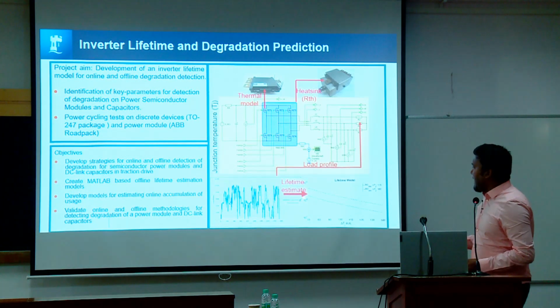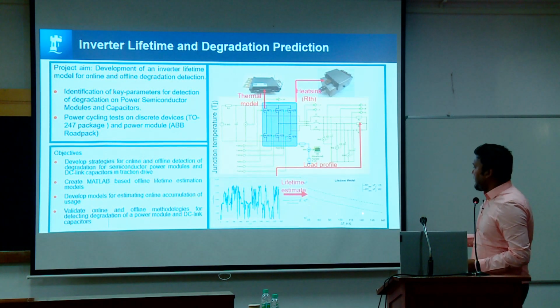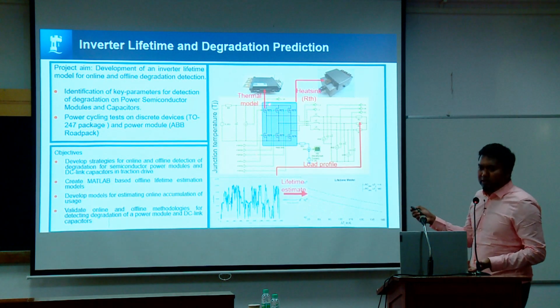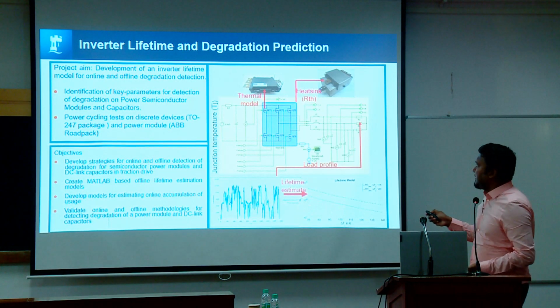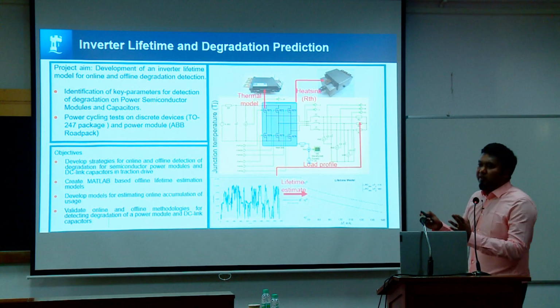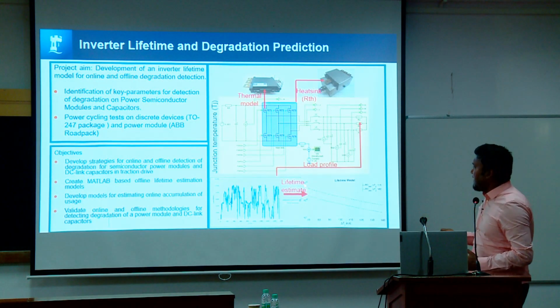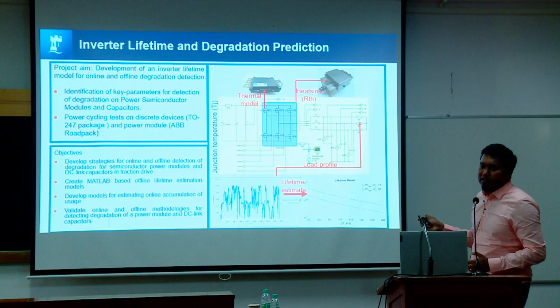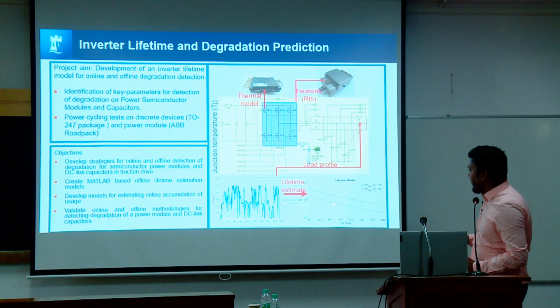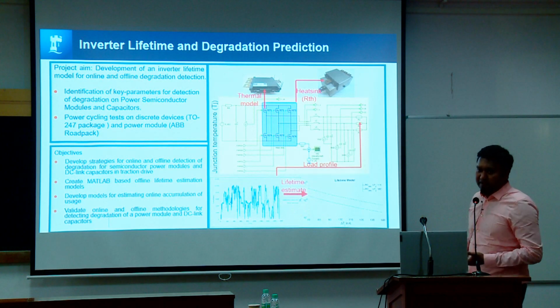And we can also get these lifetime models. Usually we can create those models as well. Essentially, you run these modules at different delta T's and find out how many cycles it takes to fail these modules. Then you fit a line for delta T versus N, which will give you a lifetime model.